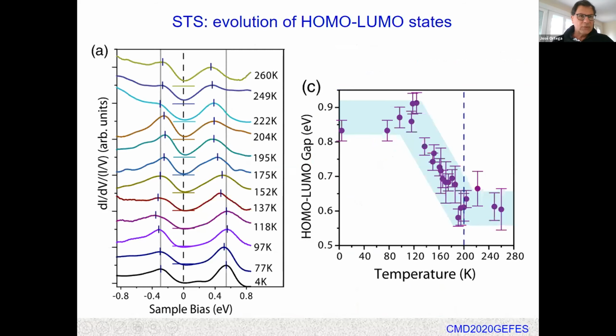Now we turn our attention to the evolution with temperature. We start with the evolution of the HOMO and LUMO states as observed with STS. Here we have the spectrum at different temperatures, and these tick marks indicate the maximum for the HOMO state or for the LUMO state. And in this figure on the right, we can see the HOMO-LUMO gap as a function of temperature, and we can notice this decrease in the HOMO-LUMO gap that goes from 0.85 eV to 0.6 eV in a temperature range between 120 and 200 Kelvin.